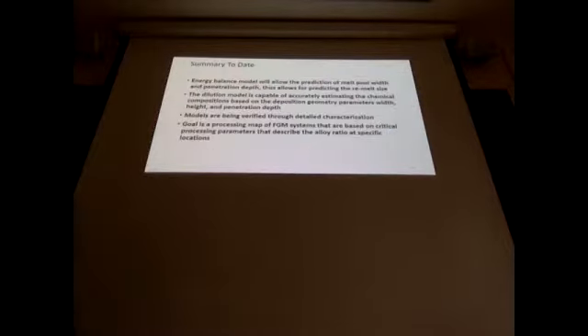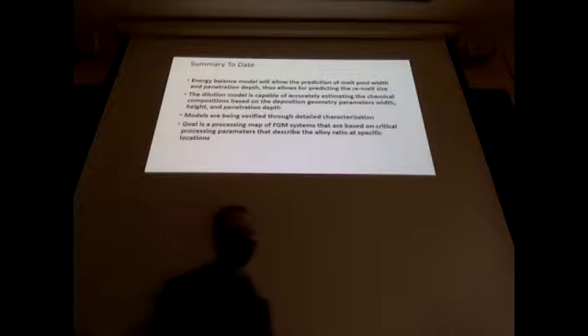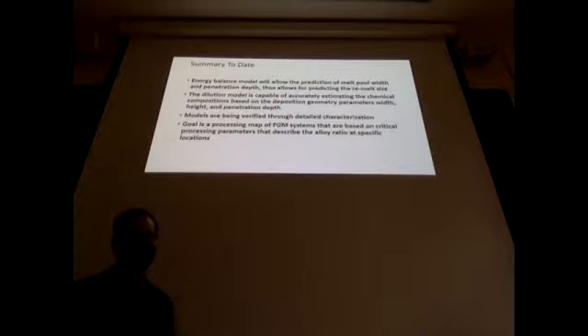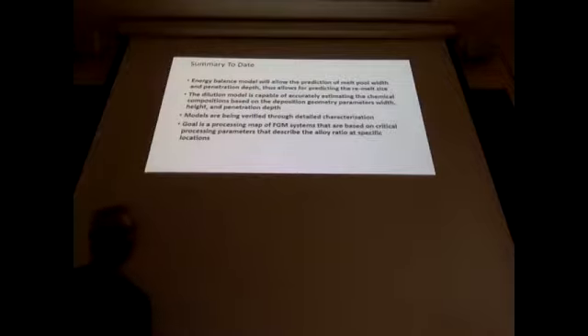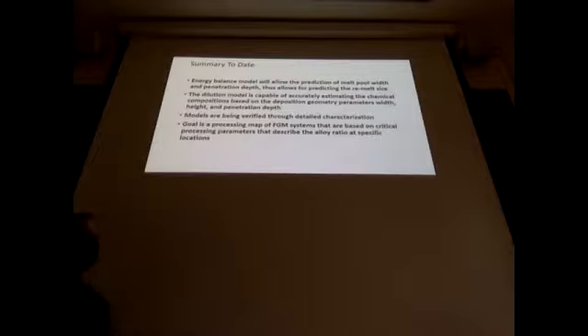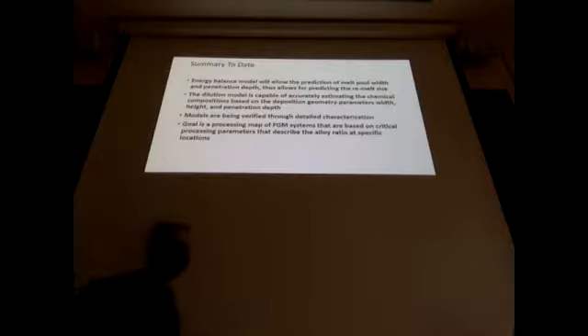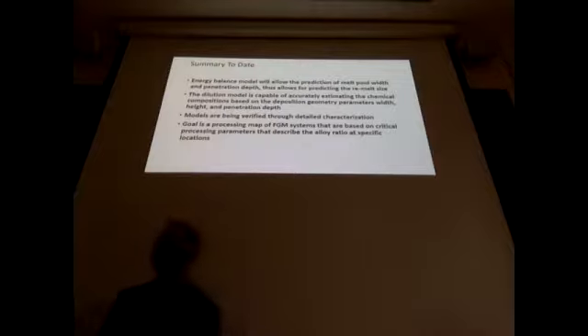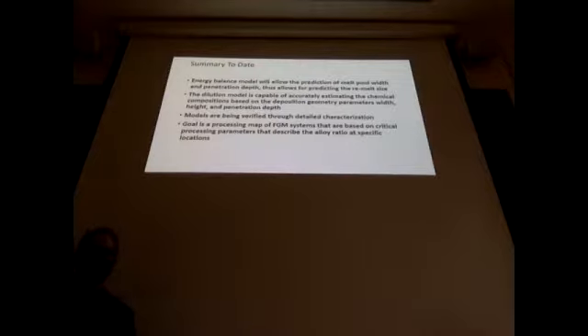And the summary to date on that project is that we think we got a decent, simple energy balance model to help predict the melt pool and penetration depth, and allows us to understand how the remelt size is impacting our part. And then we also hope that we have a dilution model that we can use to predict how our composition changes, not only in the build direction, but also in the lateral direction as well. Right now, these models are being verified by detailed characterization of the test cases that we made. And the goal is, actually, we're trying to build a map. This will be our test case map, but the idea is that we can build a map for other material systems as well.